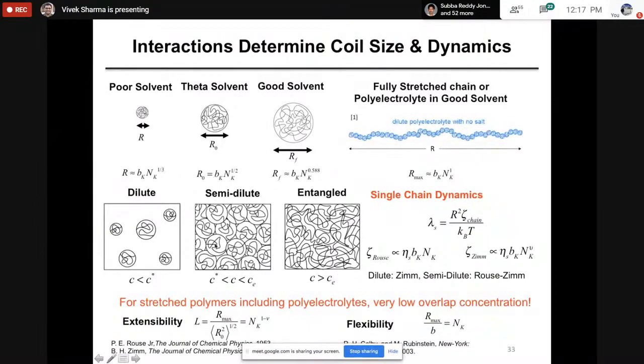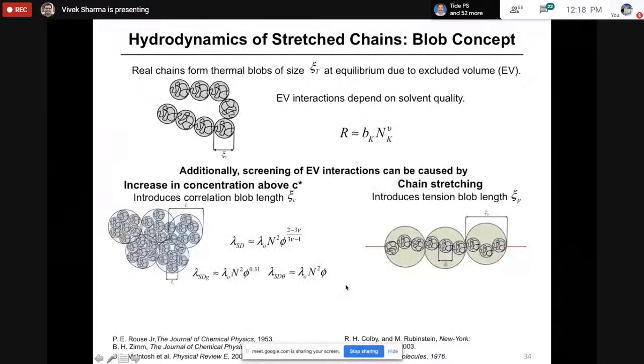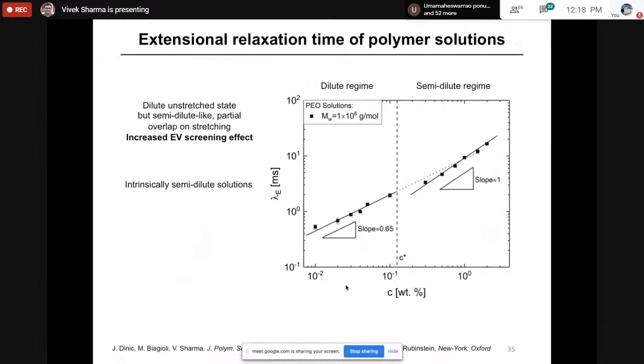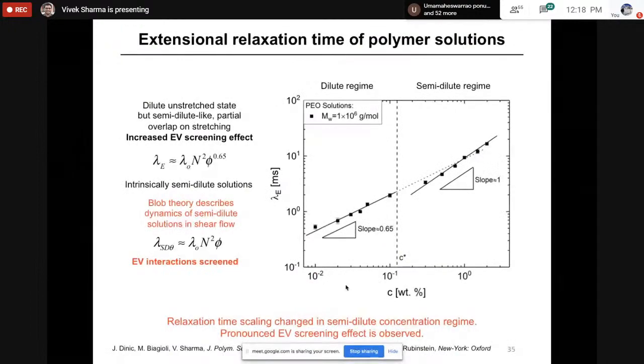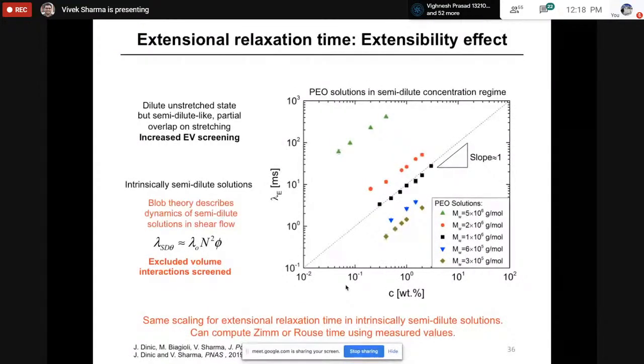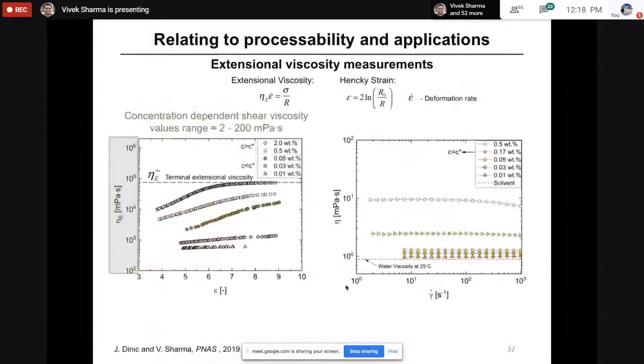In semi-dilute solutions, which are intermediate, it seems that you need to account for local behavior using Zimm theory, global behavior using Rouse theory. Now, again, details of this are relatively involved, so I'm going to skip some of these details and essentially mention this, that by using blob theory and a detailed understanding of polymer physics, we were able to show what leads to 0.65 and 1 concentration dependence. And my student Yelena, who was an overachiever, really went and verified that you do get slope of 1 for these many different molecular weights.